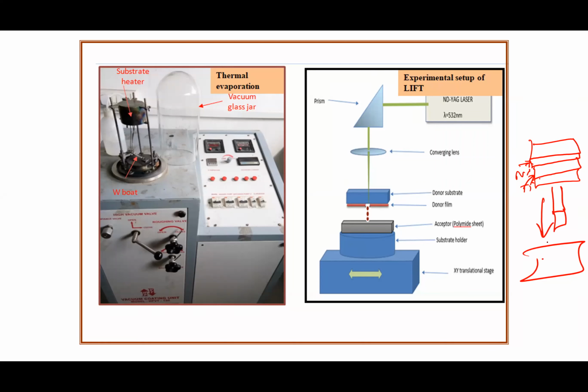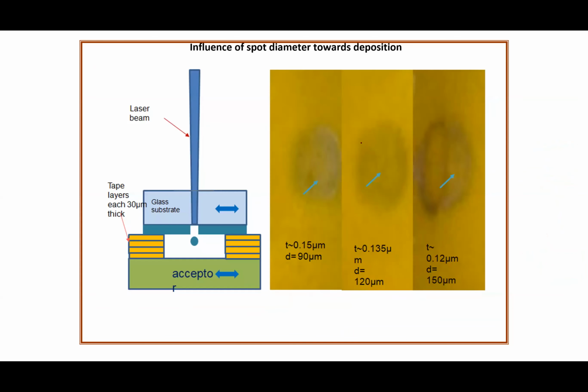This is towards microelectronics printing, where people have to prepare a mask. Here you don't require that mask. You can just directly give your drawing and do it. Okay, so this is a preliminary result which we did. We had a small polyimide sheet. We made our own XYZ stage, and this is a donor substrate and this is a donor film. Using thermal evaporation, we fabricated a small thin copper sheet, and we tried to transfer the copper. In fact, this is a kind of deposition which we could observe.